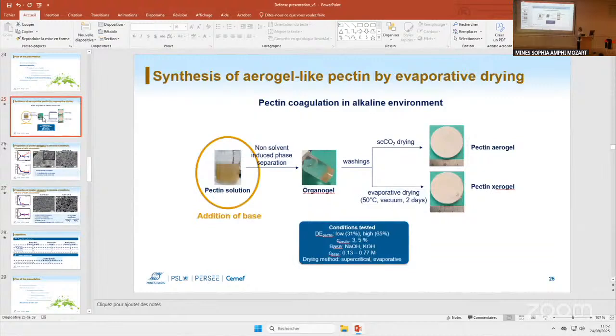On the other hand, when you treat with sodium hydroxide, you also demonstrated that when you don't use a lot of sodium hydroxide, the network is not so strong to resist a regular drying. So it brings again the fact that potentially it could be great to have really a hydrogel, meaning a 3D structure before the exchange of the solvent, and to design a hydrogel which is strong and can resist the solvent exchange and then the drying, and ideally evaporative drying.